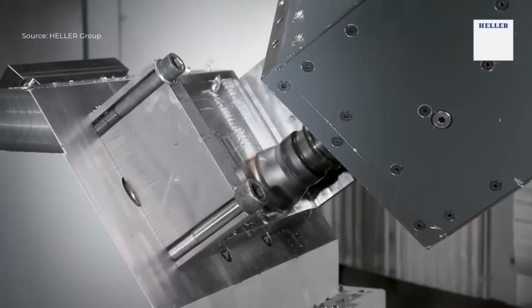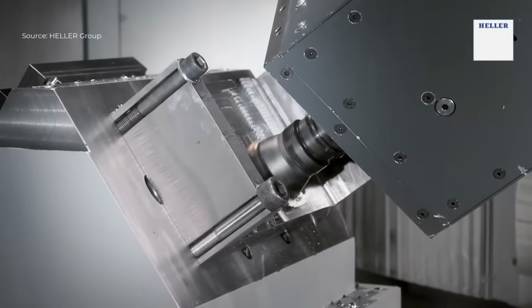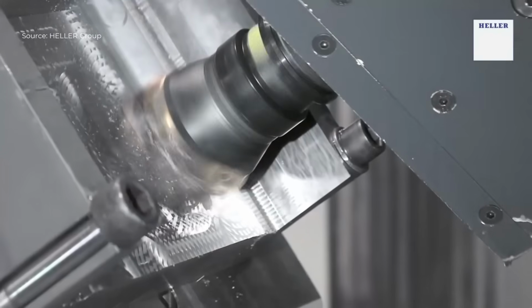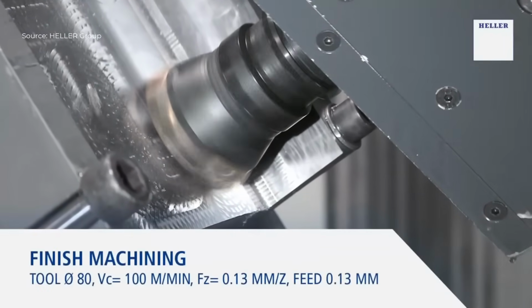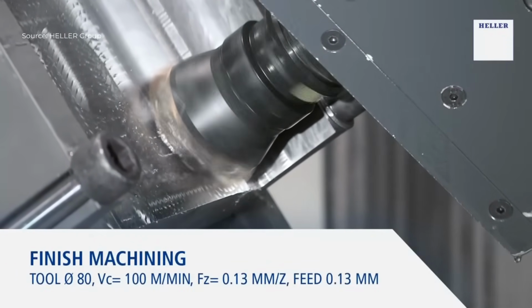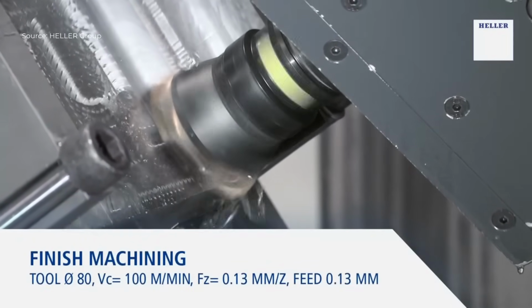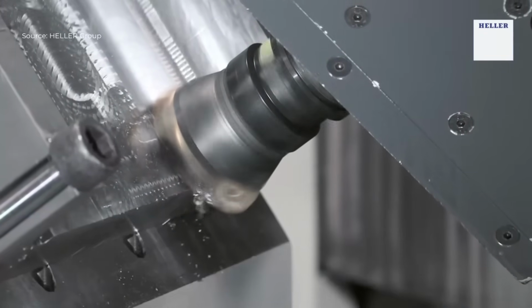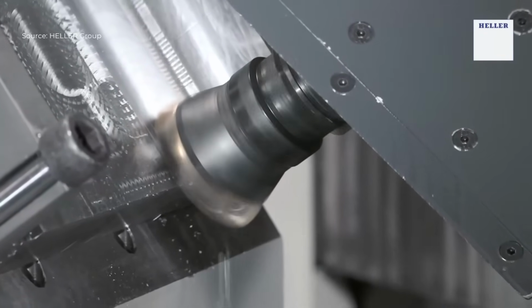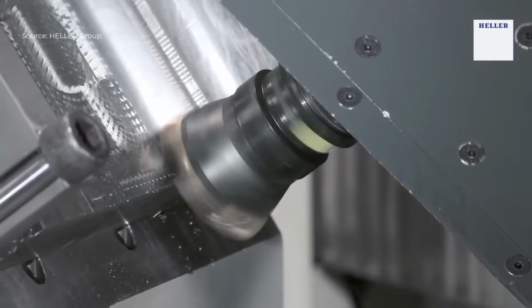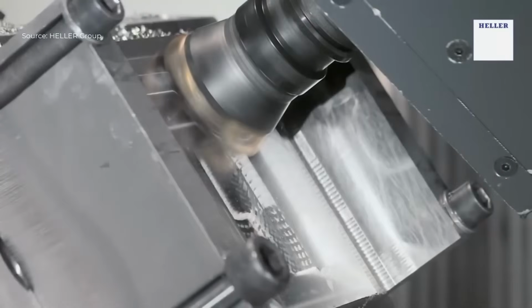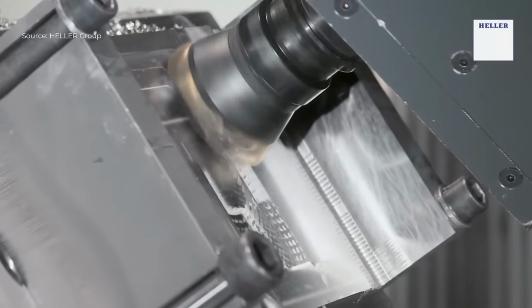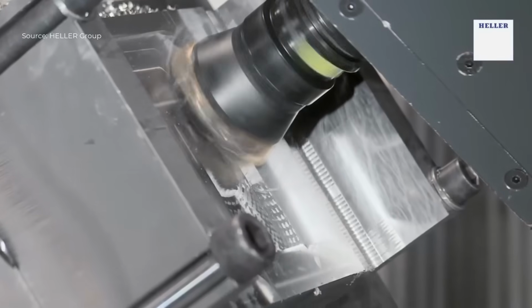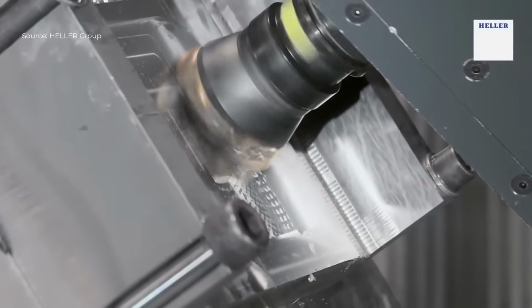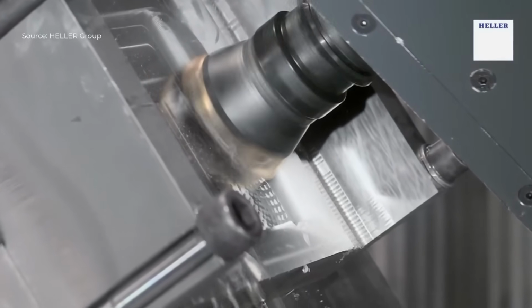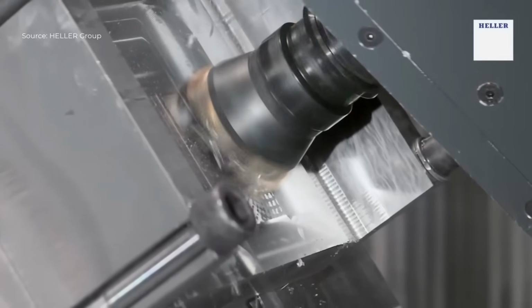Finish machining is then done with a Ø80mm tool at VC equals 100 meters per minute, FZ equals 0.13 mm/Z, and a feed of 0.13 mm to achieve precision. The machine mills thin walls with thicknesses ranging from 0.5 to 2 millimeters and conical angles of 1 degree to 3 degrees, demonstrating high accuracy performance in structural titanium parts.